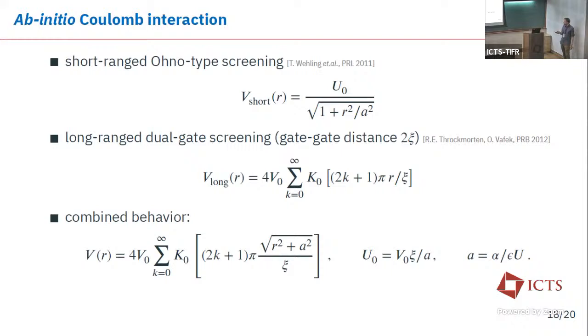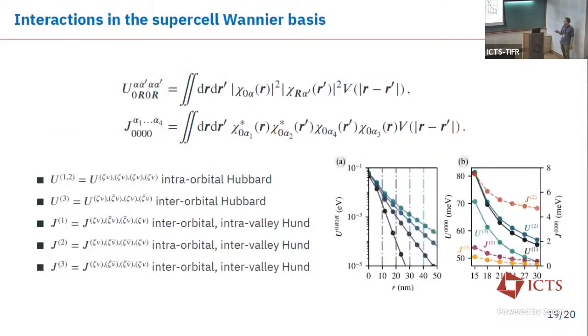We actually take this interaction now and we project it to our supercell Wannier function. So we basically calculate those integrals, the first one being Hubbard interaction parameters, the second one being density-density interaction parameters, and the third one being all kinds of exchange interactions. And we clearly see that the interactions of this model are dominated by Hubbard-type interactions. On the right-hand side, you see all the local interaction terms where U1 and U2 are intra-orbital Hubbard interactions, and U3 is the inter-orbital Hubbard interaction.